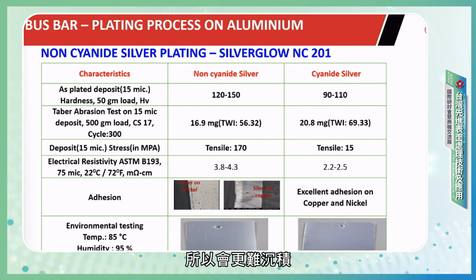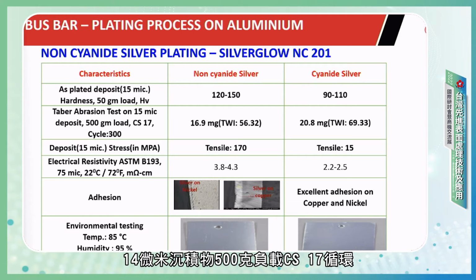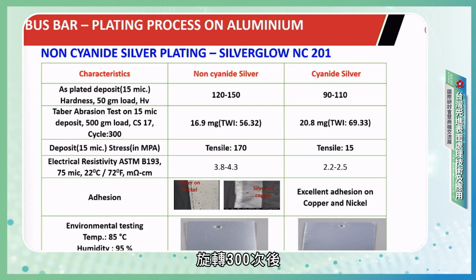And since it gives a harder deposit, the Taber test wear resistance is also better. We tested a 15 micron deposit with a 500 gram load, CS 17 cycle. After 300 cycles of rotation, we see a loss of around 16.9 milligrams as against cyanide's 20.8. So in terms of Taber wear index, the non-cyanide deposits are better.